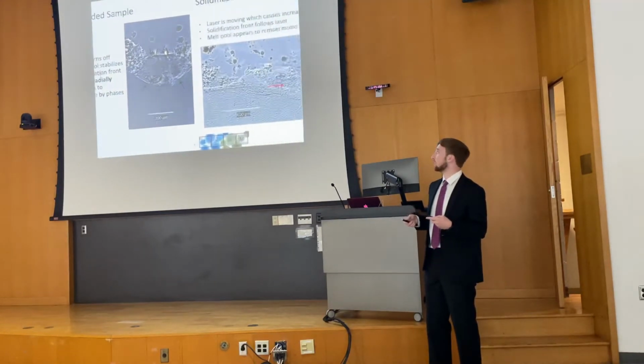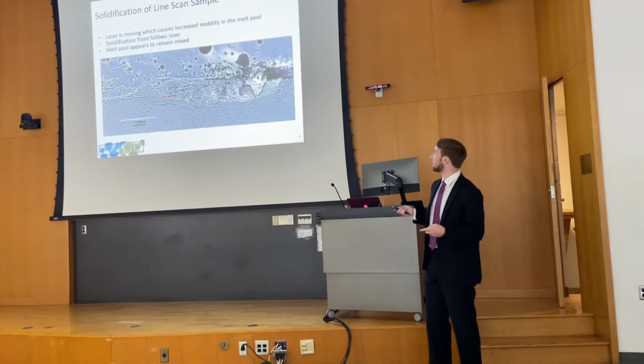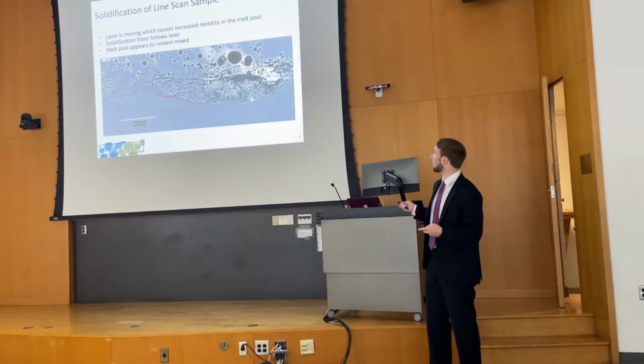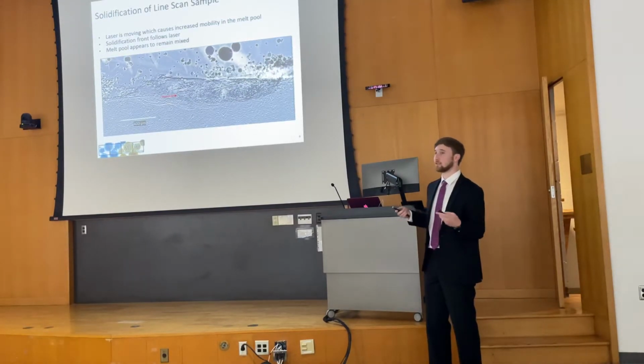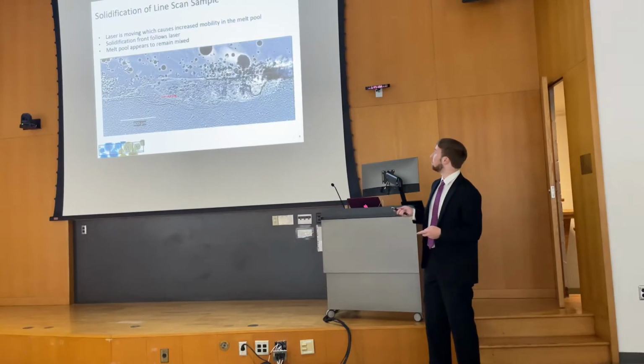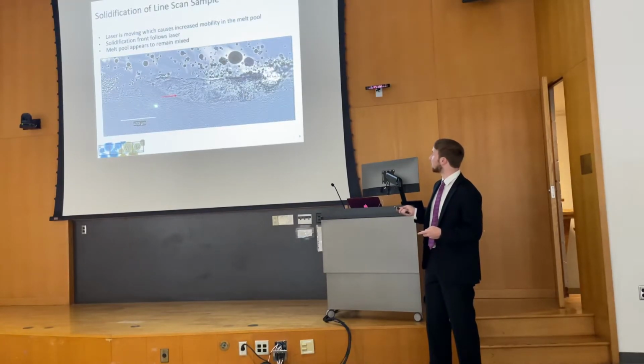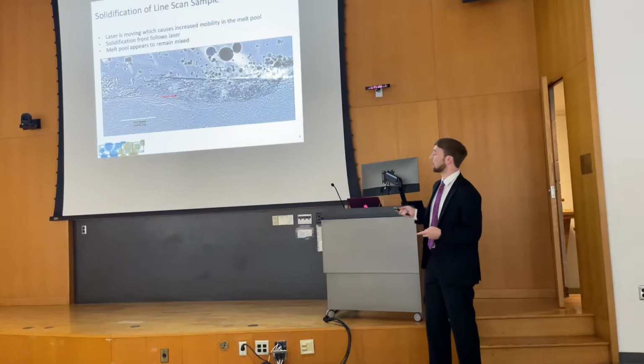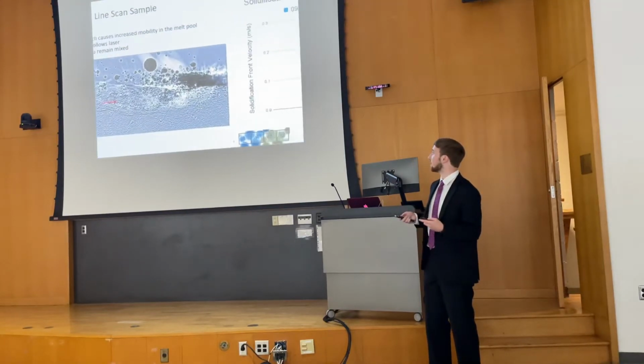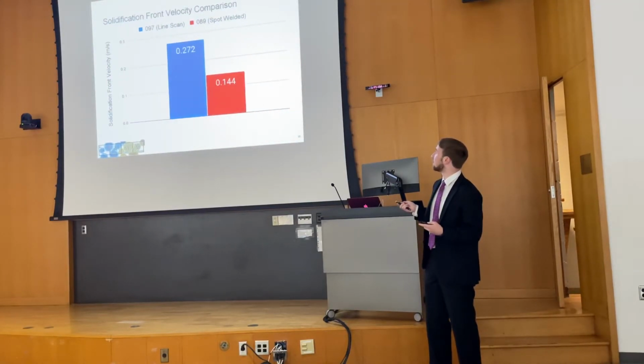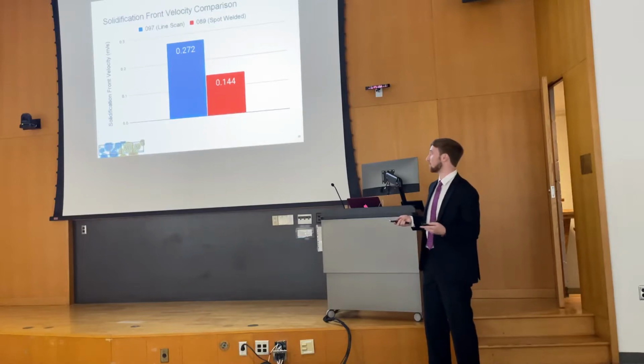So we also looked at the solidification of the line scans and found that the laser moving across had a higher impact on the velocity of the fluid. And the melt pool appears to remain mixed as the solidification front moves horizontally rather than radially. So to quantify these, the solidification front velocity was 89% faster in the line scan compared to the spot welds. So we'll be focusing on the line scans for the rest of the presentation.